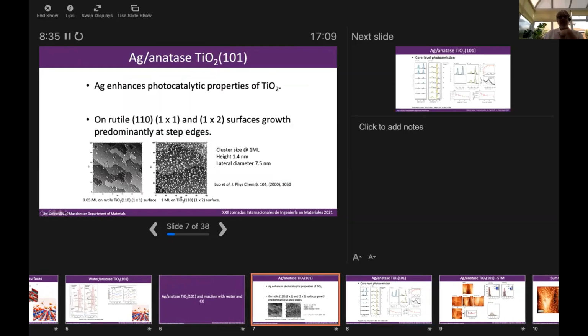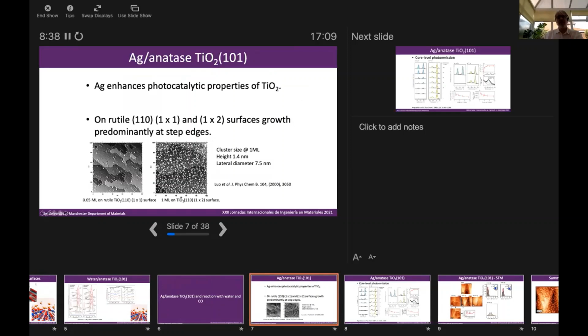So we knew that silver and rutile had been studied previously, and we knew that silver supposedly enhances the photocatalytic properties of titanium dioxide. On the rutile 110 studies that had been done previously, it was found that the cluster size at about 1 monolayer, so this is 1 layer of silver atoms per titanium atom, was about 1.4 nanometers high, and the lateral diameter was about 7.5 nanometers, so quite large.